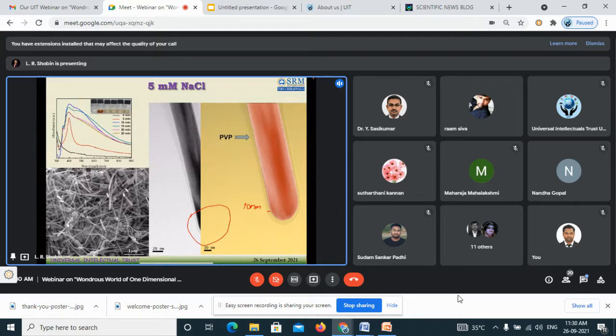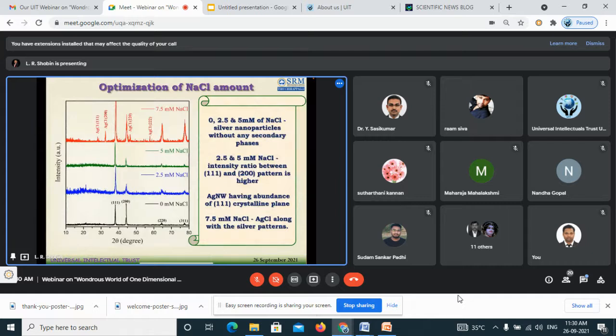If you increase the PVP, you won't get a conducting wire, because it will wind over this silver nanowire, which will decrease its conducting property. But the thickness is 10 nanometers, so the electrons can tunnel through this thickness, so they are still conducting in nature. And if you want to remove this PVP, you just wash it away with water.